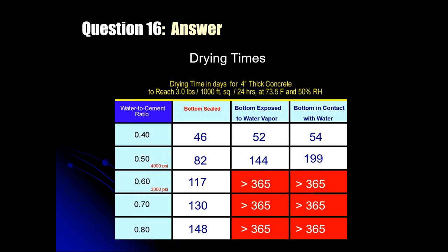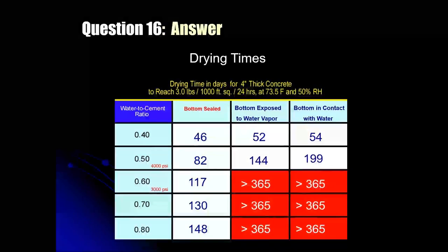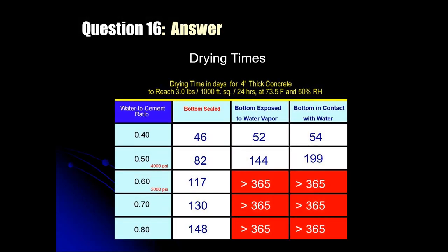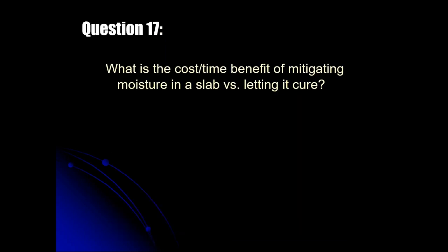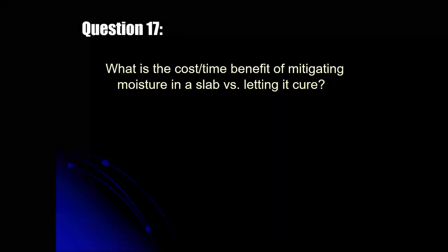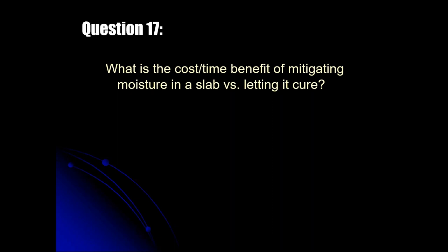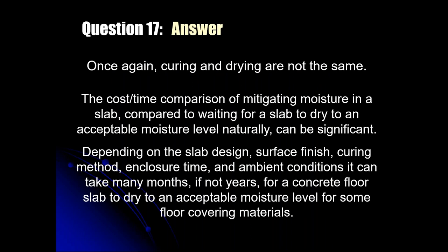And if you look at the slab that wasn't adequately protected, or the slab that actually had water in contact, even in the laboratory, those slabs never reached the target level in less than a year. It didn't happen. So drying and curing are two distinctly different time periods. What is the cost time benefit of mitigating moisture in a slab versus letting it cure? Again, I think they mean dry. As I said, they're not the same.